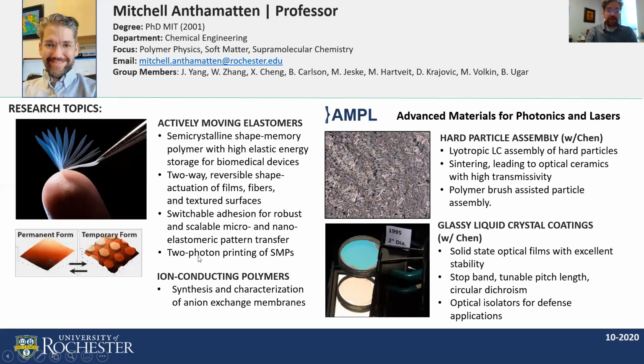We've also, a new direction is M. Jeske is trying to develop new two-photon printing of shape memory polymers. So we're envisioning these high-resolution structures that can be printed with a two-photon printer, which can go to submicron dimensions. And we'd like to have a shape memory effect there to do things like the switchable adhesion, but also we envision some interlocking surfaces that can interlock when they're triggered. Our lab is also working with ion-conducting polymers for anion exchange membranes. In short, we're trying to integrate hydrogen bonding groups. We have a long experience working with hydrogen bonding groups to improve the mechanical properties and water management of these anion exchange membranes.